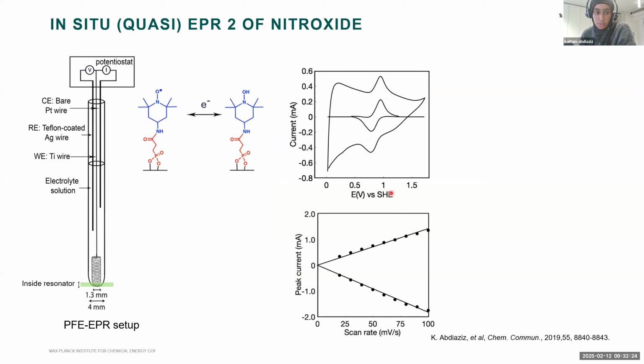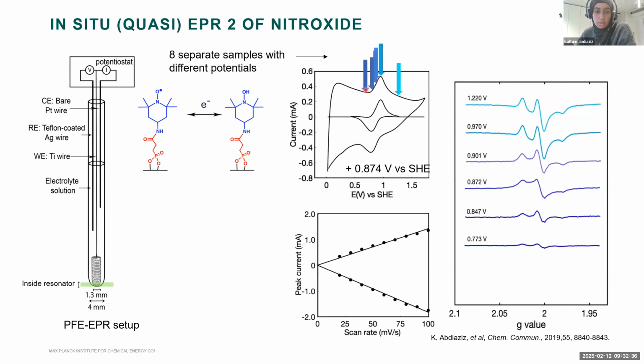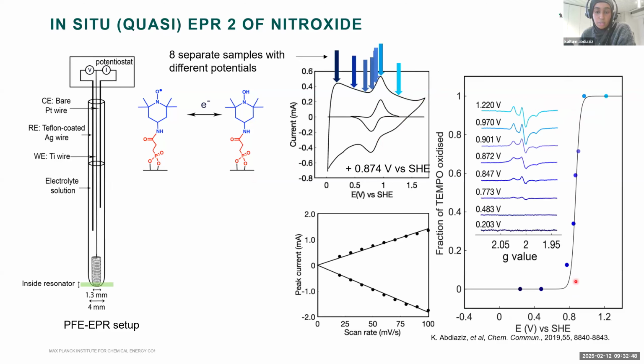So the one system that we worked on is these nitroxide molecules that were immobilized covalently onto the electrode. Here, if you look at the CV, you can see two redox peaks. If you apply the potential and measure the corresponding EPR, we see that the signal is disappearing. And if you plot that against a Nernst curve, we see that the midpoint potential that we obtained from the Nernst curve matches very well with our CV. So with this, we are fairly certain that we have a direct and accurate potential control.